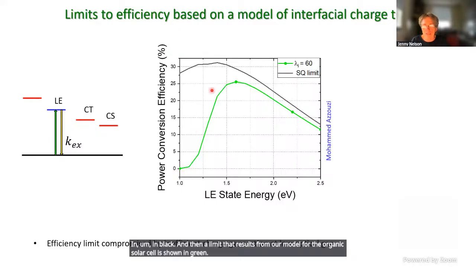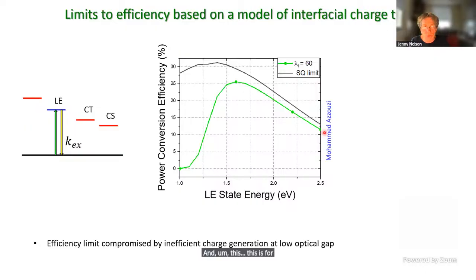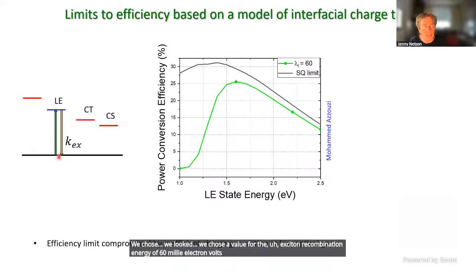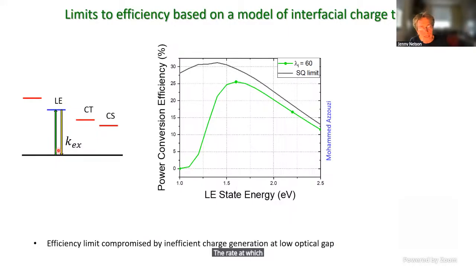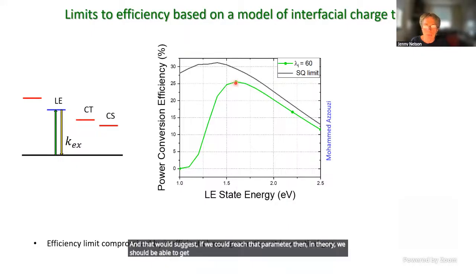And for this, we needed to choose values of parameters, and in this case we chose a value for the exciton recombination energy of 60 millielectron volts. That's really determining the rate at which this excitonic state would decay to ground, and that would suggest if we could reach that parameter, then in theory we should be able to get to a power conversion efficiency of maybe 25%, and that would be at a somewhat larger bandgap energy than what is normally studied.